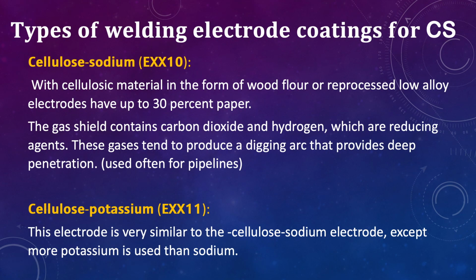The cellulosic electrode can be cellulosic sodium based, EXX10, for example 6010, 7010, with cellulosic material in the form of wood flour or reprocessed paper, up to 30%. The gas shielding contains carbon dioxide and hydrogen, which are reducing agents. The gases tend to produce a digging arc that provides deep penetration. So, it is often used for pipeline, especially for the root. Cellulosic potassium based, which is EXX11, that is 6011, let's say 7011. These electrodes are very similar to the cellulosic sodium electrode, except more potassium is used than sodium.